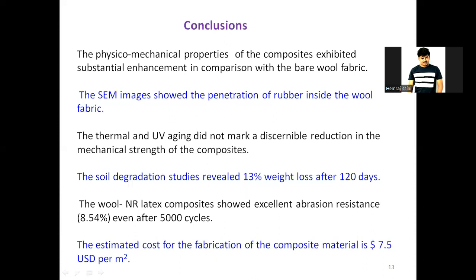Now coming to the conclusions, we analyzed the physicomechanical properties of the composites, and we found that there is a substantial increment in comparison with the bare wool fabric. The SEM images showed the penetration of rubber inside the wool fabric, because the latex penetrates inside the wool fabric, and on both sides we are getting a uniform coating. Thermal and UV aging didn't cause much reduction in the mechanical strength of the composites. We also performed soil degradation studies. We kept the composites in the soil for 120 days, and we found that only 13% weight loss was observed, which indicates that natural rubber, though it is a natural material, after cross-linking or vulcanization, has a restriction in biodegradation.